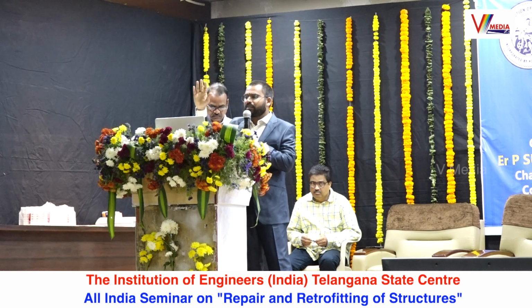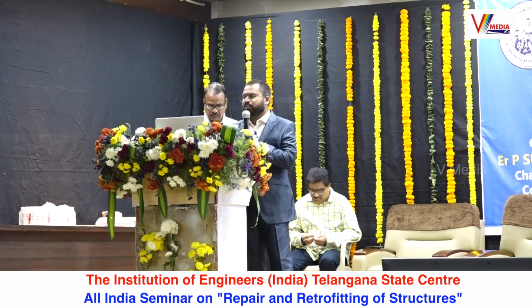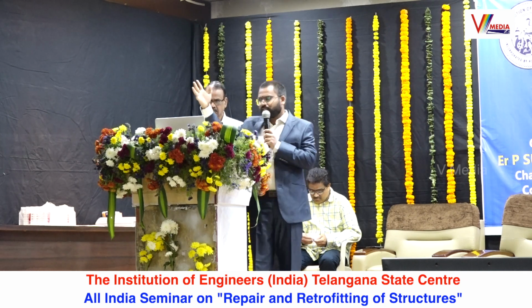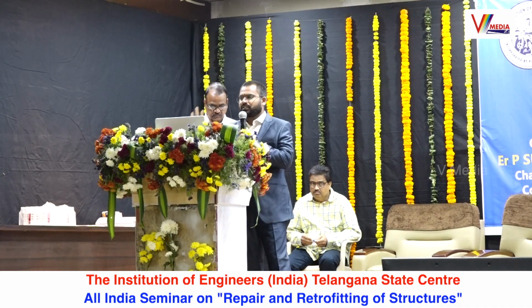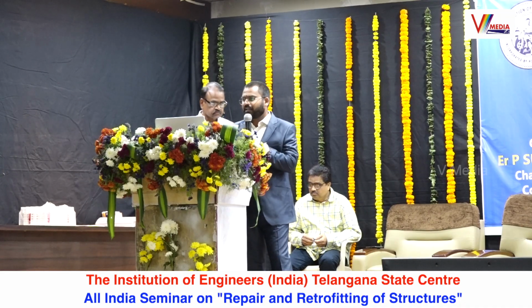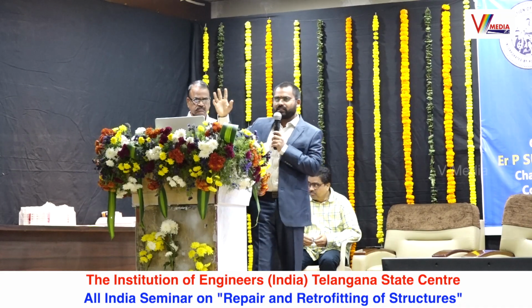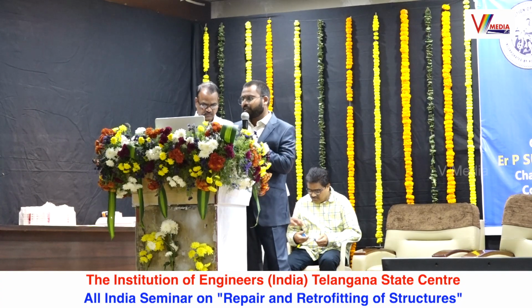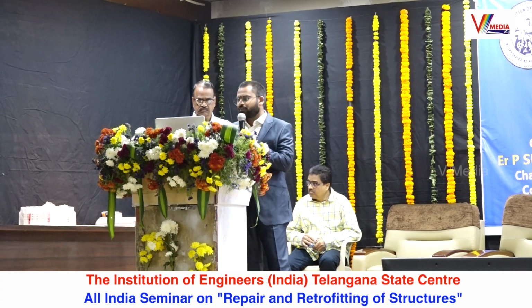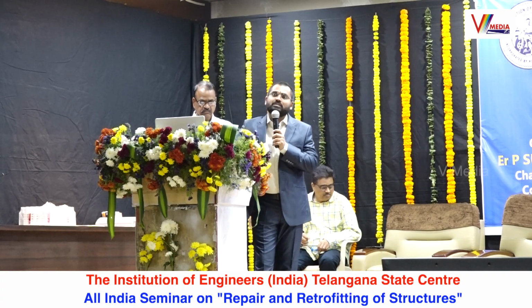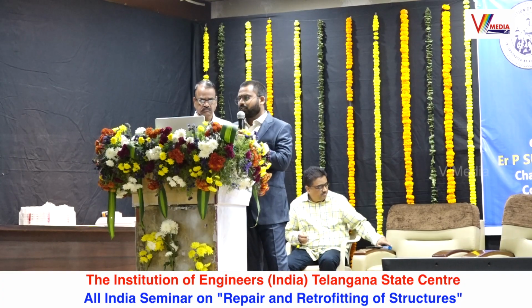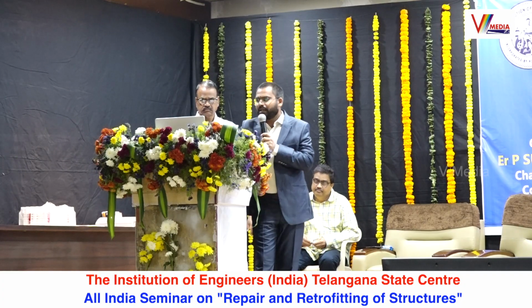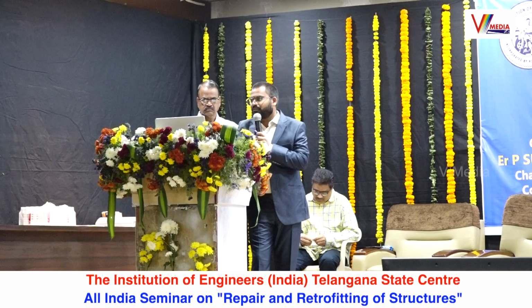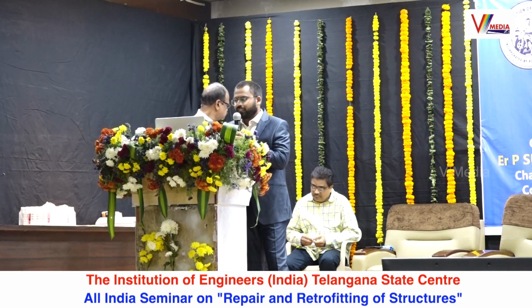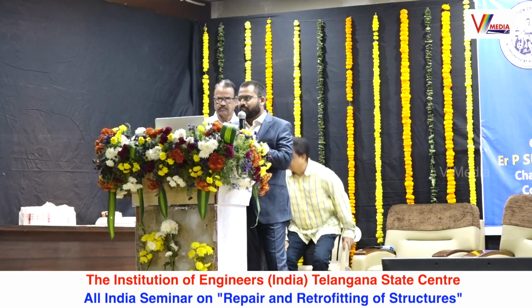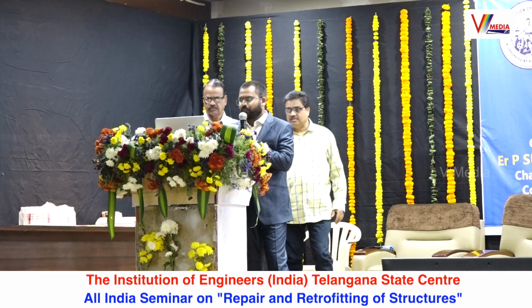Now coming to the damage stages: the first stage is formation of white patches. Second stage, change of color of the patch. Third stage, development of hairline cracks. That is where maintenance activity has to be taken care of. If not, cracks multiply and widen, giving access to oxygen and moisture, and then spalling of cover concrete and snapping of ties. The final stage is bulging of concrete. So with this, I think I'll end my presentation.